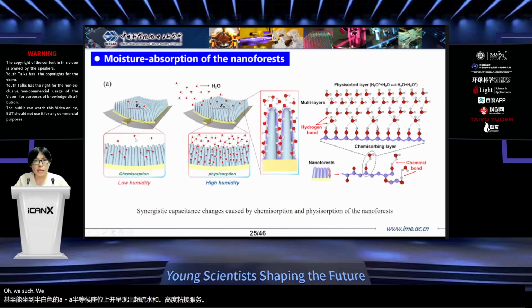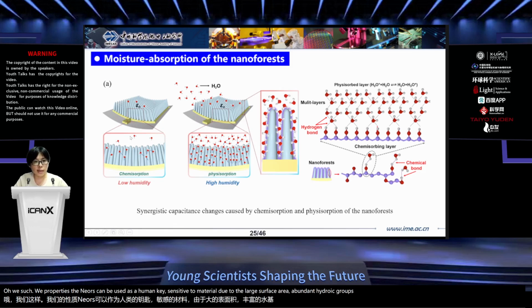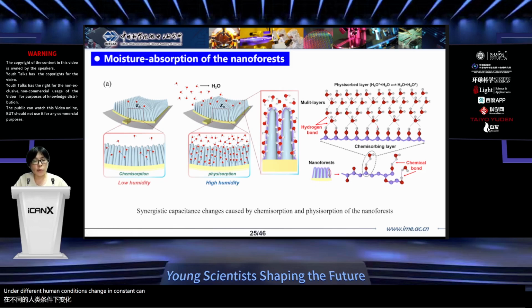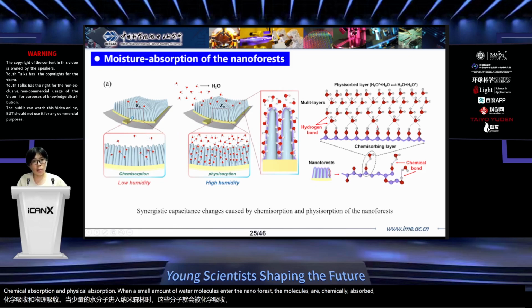With such wetting properties, the nanoforest can be used as a humidity-sensitive material due to the large surface area and abundant hydrophilic groups on their surfaces. Under different humidity conditions, a change in dielectric constant can be generated through the synergistic effect of chemical absorption and physical absorption. When a small amount of water molecules enter the nanoforests, the molecules are chemically absorbed to the functional groups on the surface through hydrogen bonds. In the process, the water molecules occupy the active sites on the surface one by one.